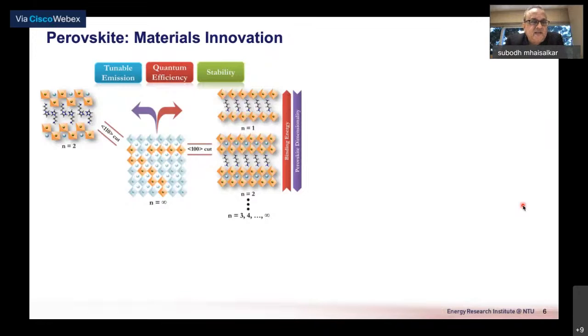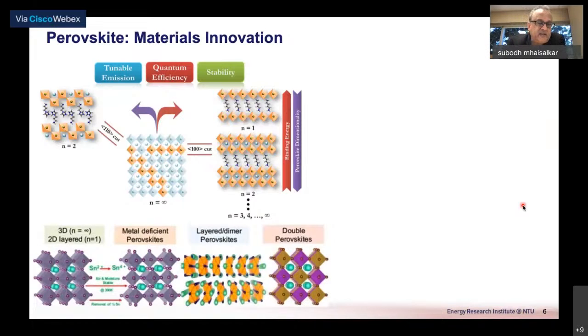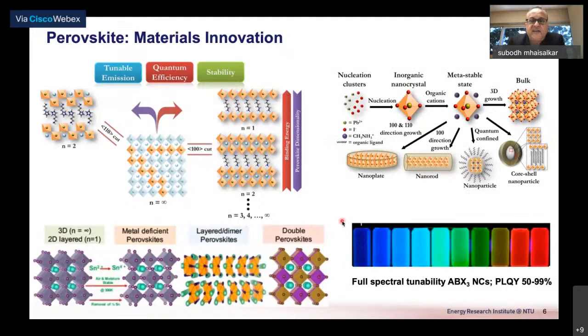What is exciting in perovskites is really the possibility of the structural diversity of this material, and you can tune the emission, you can tune the optoelectronic properties as well as stability using different configurations of perovskites itself. This is even further extended by the possibility of chemical, elemental substitutions. And you can have metal deficient perovskites, a variety of layered or dimer perovskites, as well as double perovskites. It's estimated that this variation in composition as well as in structure leads to more than tens of millions of possible combinations of perovskites. And that's why a lot of work is also now being done in using artificial intelligence or machine learning in designing of these materials.